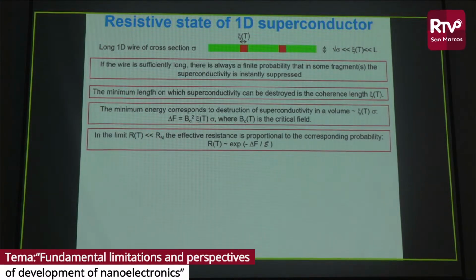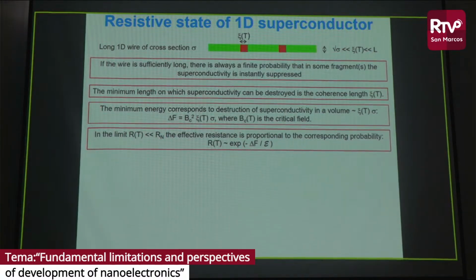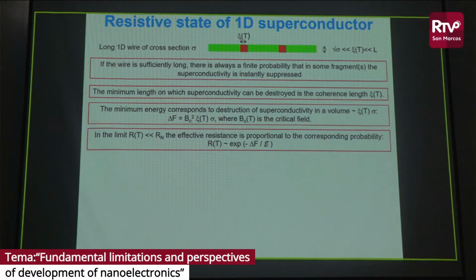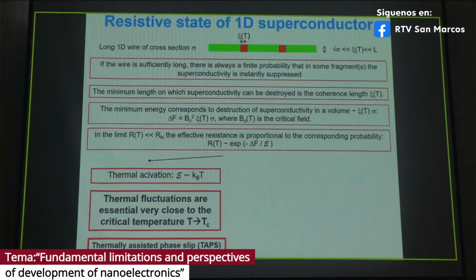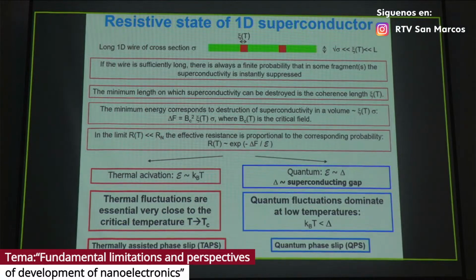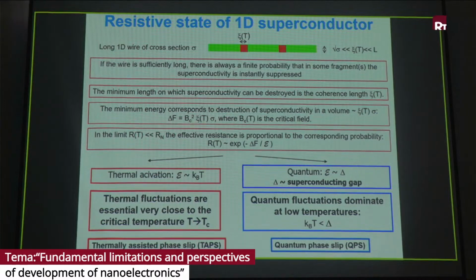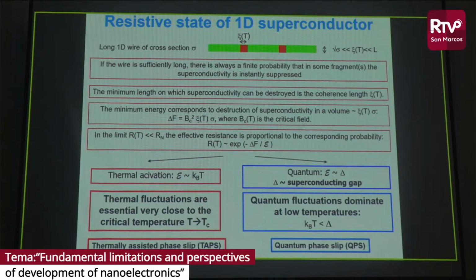Theories show that the energy required to suppress superconductivity is proportional to the free energy per volume. And the minimum volume is the cross-section of the wire times the coherence length. The probability of such a process depends exponentially on this energy barrier to suppress superconductivity, normalized by some energy. And the whole story is about what this energy is. If we speak about thermal fluctuations, it's just k_B T, the thermal energy. And it appears that this contribution is important at temperatures sufficiently close to the critical temperature. But there is a much more interesting story, because the superconducting state is a macroscopically coherent state where the order parameter is itself fluctuating. This contribution of quantum fluctuations is valid for all very thin superconductors, even at very, very low temperatures.